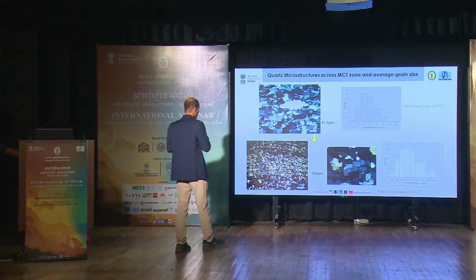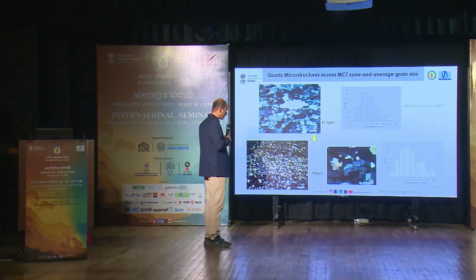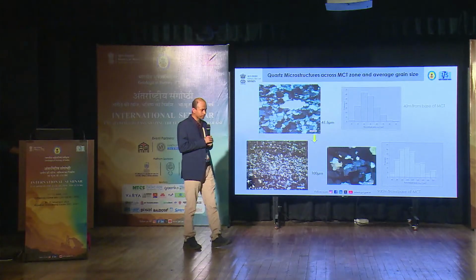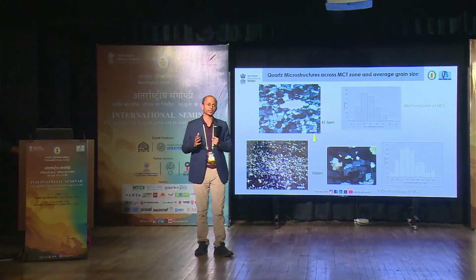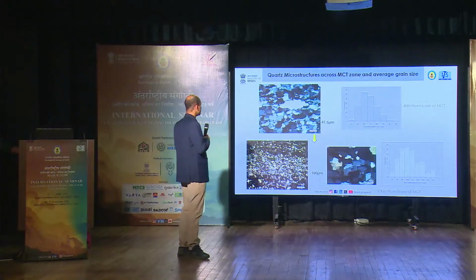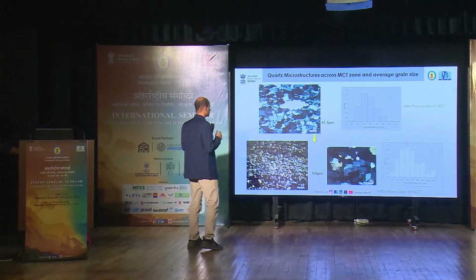And then the next sample was collected from 930 meters from the base of the MCT. Here we see there has been a sudden marked increase in the average grain size. It has jumped up to 100 micron.